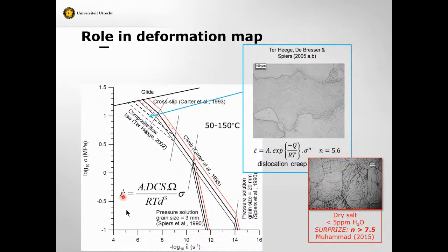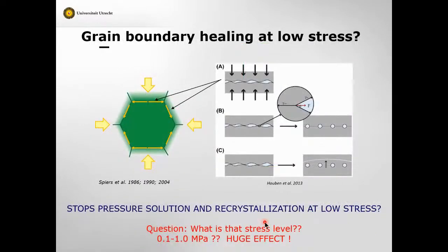How does that figure in the log stress, log strain rate plot? Okay, this is now put the other way around. These are high strain rates, these are low strain rates. Here's the dislocation creep behavior. This is mostly where this recrystallization occurs, in this regime with n about 5. Probably it goes on alongside dislocation creep, affecting the flow strength maybe by a factor of 2. Once you get down here, you get into this pressure solution, linear creep regime. What a surprise, you dry this stuff, and n changes from 5 to 7.5 straight away. Okay, so there's all sorts of interesting and complex stuff there.